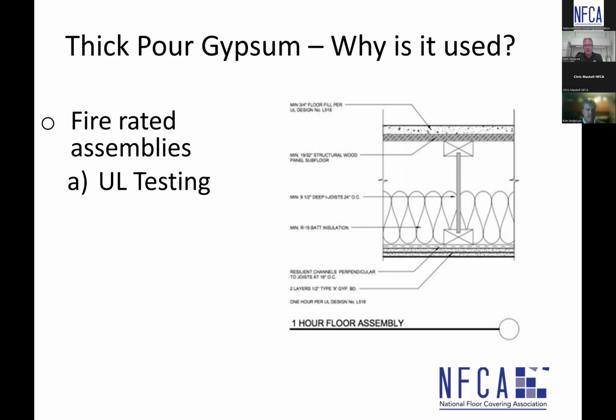Like 1.5 to 2 inches, or? Not very common. They will test that. Their minimum thickness for these thick pour gypsums is very commonly 3/4 of an inch, so they will typically test at 3/4 of an inch as part of an assembly, because that's their minimum thickness. Is that what you were asking, Chris? Well, in general, the title of this presentation is thick pour gypsum, and thick doesn't quantify anything, does it? So what do you mean by thick? How thick?